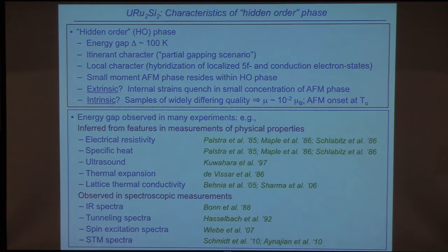Okay, so a little bit about the characteristics of the hidden order phase. So it certainly has an energy gap of about 100 Kelvin. It has itinerant character, which I think is consistent with this partial gapping scenario that we proposed. It has to have local character, so you have hybridization of localized 5f and conduction electron states. And as you've seen, the small moment antiferromagnetic phase resides within the hidden order phase and is presumably responsible for this small moment. And I think the general view is that this is an extrinsic effect where you have internal strain which frequently causes small concentrations of the antiferromagnetic phase.